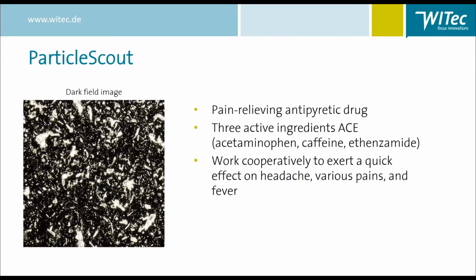Next step is clear. What about the analysis of not one single particle, but many particles? And the solution is the Particle Scout analysis tool, which allows for the automated analysis of tens of thousands of target particles. In the example shown on this slide, an analgesic, that is painkilling, and antipyretic, anti-fever powder sample was investigated with Particle Scout by first acquiring a dark field image that you see here on the left. From this image, the location and morphology of all particles is extracted automatically by the software.